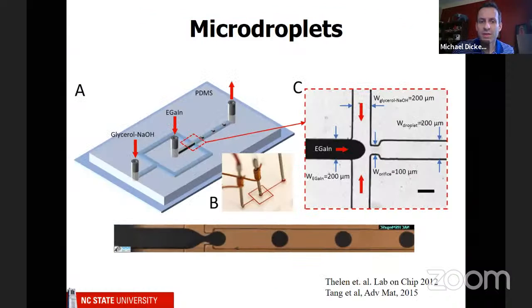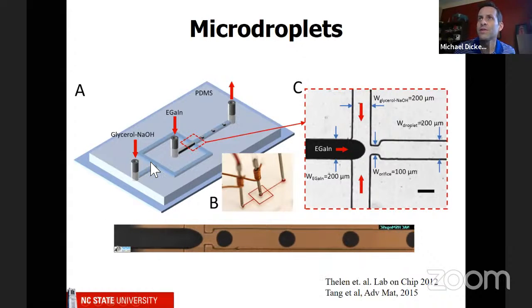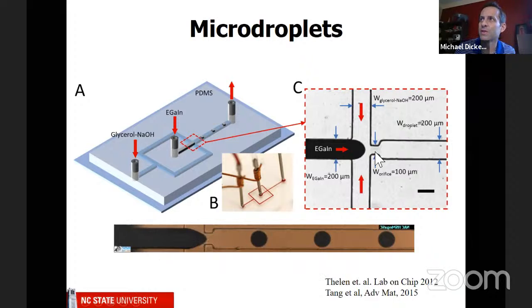We've used these same principles to control the size of droplets in microchannels. So I showed this earlier where we're pumping liquid metal. So this is what our microfluidic device looks like. We pump liquid metal as well as another solution, and we squeeze everything through this little orifice. So you can see right here, that orifice. Here's another picture of it. Just the liquid metal getting pushed through here, and then this other stream, it all converges into that orifice. Well, this is great. And we've done this.